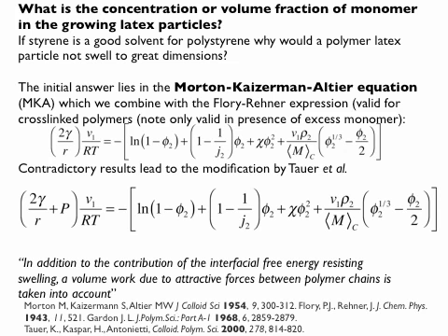So this term only is important when you use a cross-linking agent. For example, if you would use divinylbenzene in the polymerization of styrene, because basically you reduce the distance between 2 units of divinylbenzene if you use more. And then the correction term between brackets is only a function of the volume fraction of polymer used.